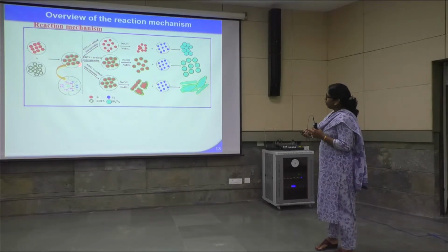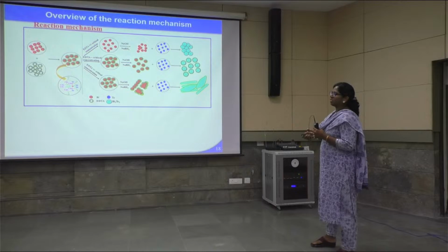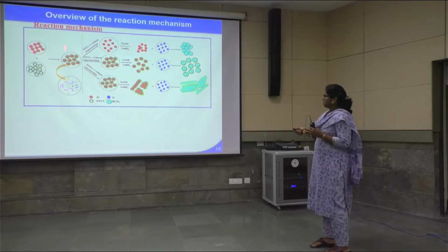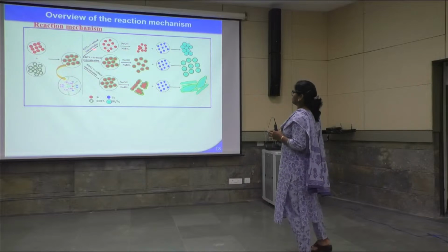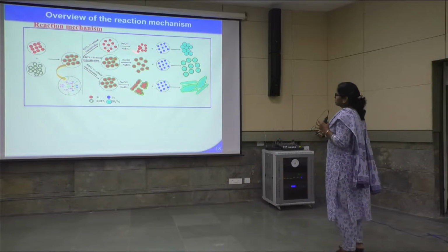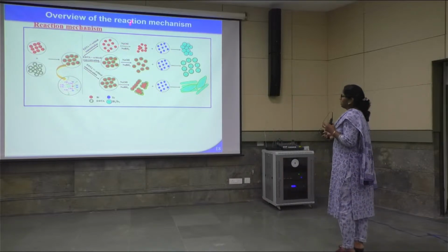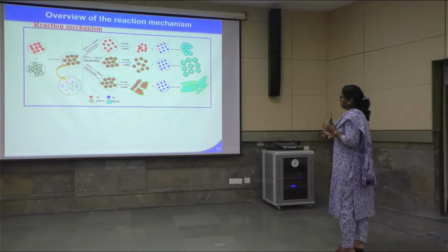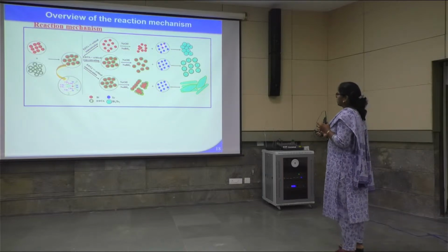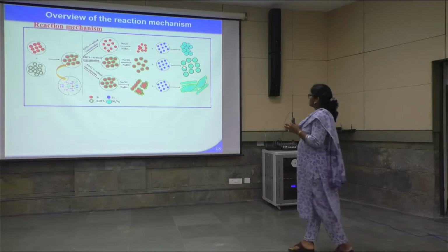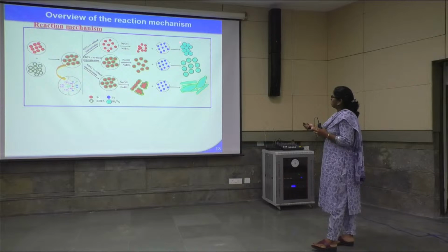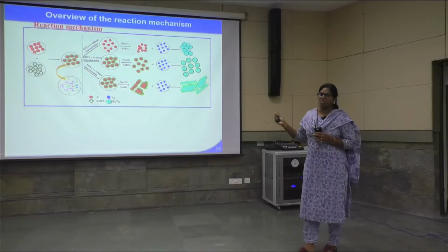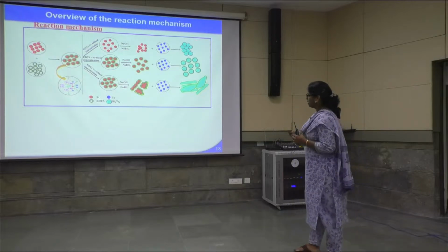When it is below the critical concentration, that means below 75, and this is the case I'm talking about when we use 50 millimolar, the lower concentration of the surfactant, then when we use sodium borohydride, the particles and the tellurium powder get mixed in such a way that a thin layer is formed, and that's how the morphology is obtained like this.